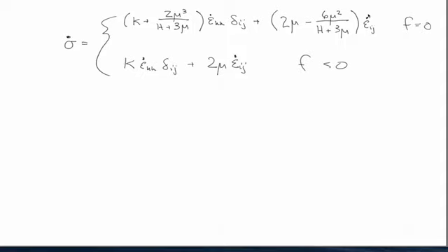So that is the full constitutive model, full stress tensor for isotropic hardening. And unfortunately, that's probably the only one we can write down the solution in closed form to. That's not true. It's not the only one, but it's very difficult to write down the solution in closed form, and that's why you see very seldom any closed form solutions to plasticity. They're almost always done in a computer.